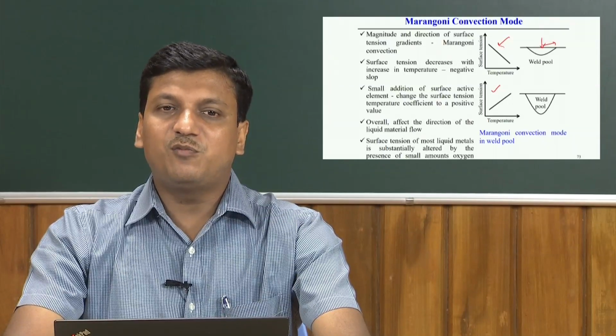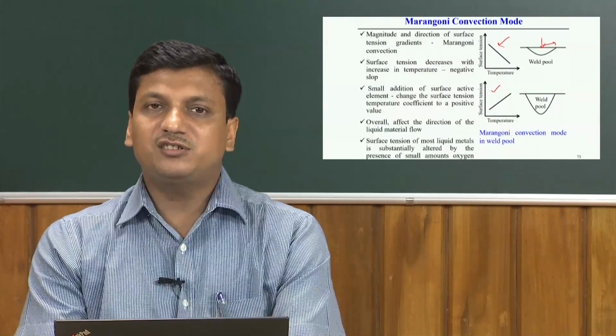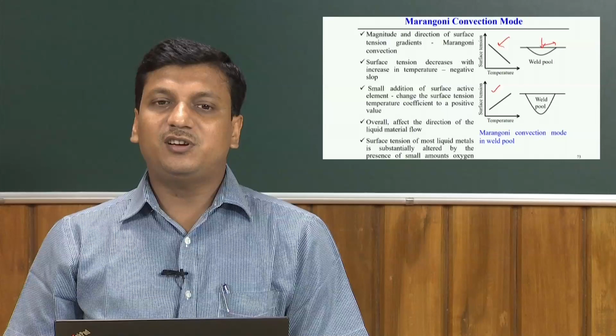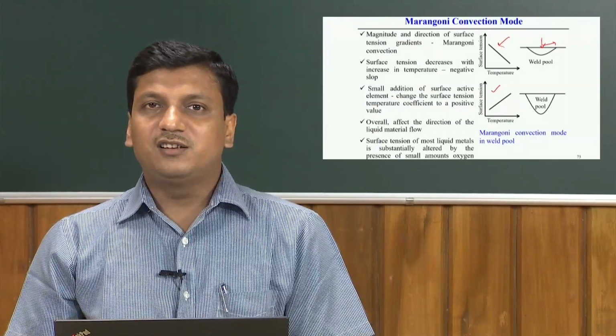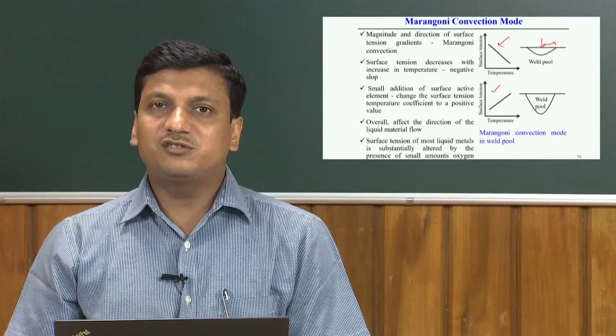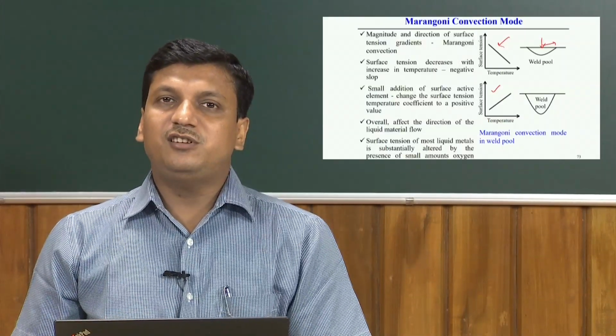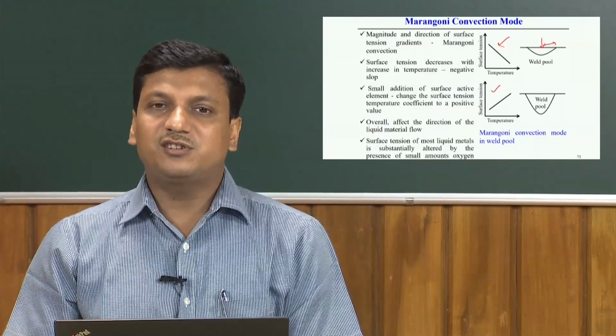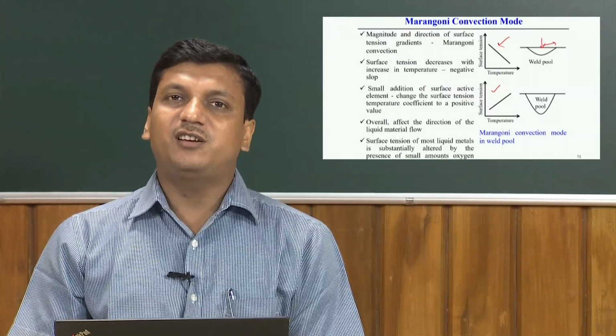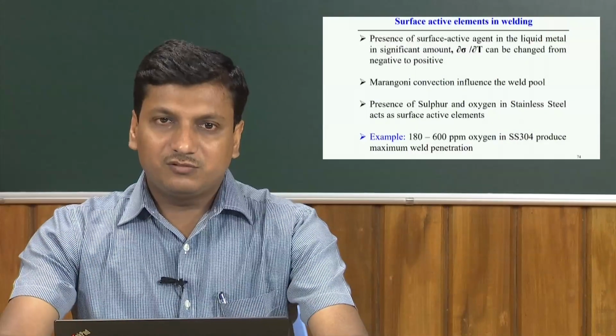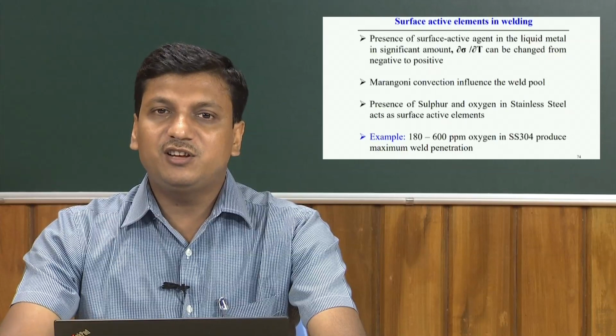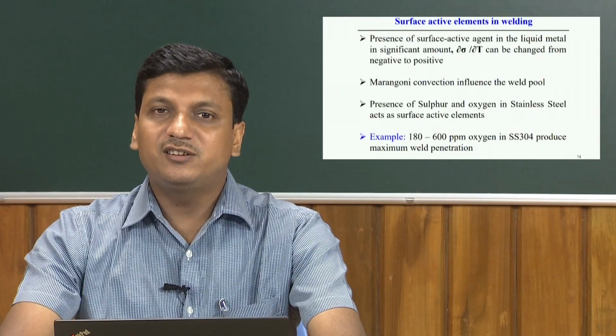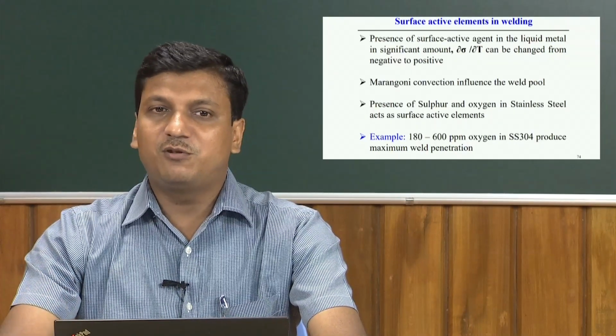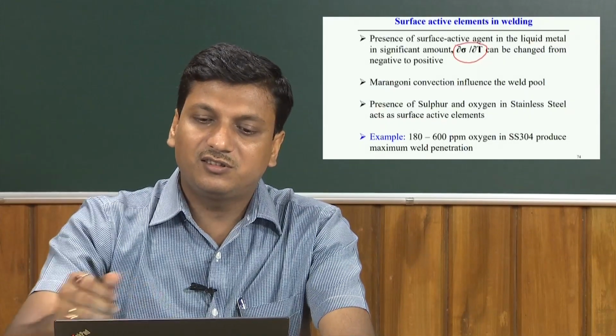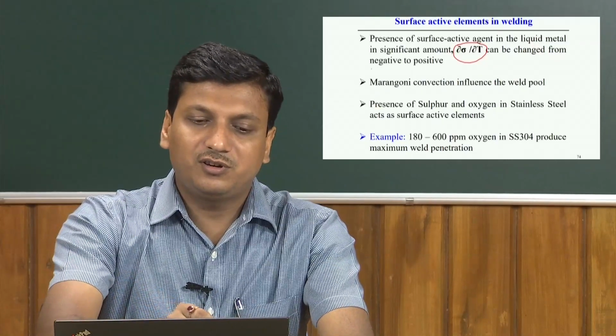Definitely, the surface tension of most liquid metals is substantially altered by the presence of a small amount of surface active elements like oxygen and sulfur. Practically, in steel, the presence of oxygen and sulfur in a certain quantity acts as surface active elements, and they alter the surface tension force and the mode of the material flow, and finally affect the size of the weld pool. Now, the presence of surface active agents in the liquid metal is significant, and that is better represented by the temperature gradient of the surface tension force, which changes from negative to positive depending upon the presence of the surface active agent.